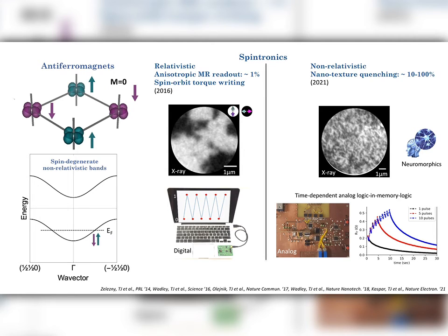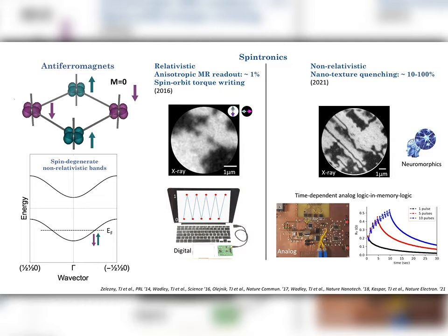And apart from imaging, we can use this electrical anisotropic magnetoresistance for the electrical readout, and then with the electrical writing and readout, we can demonstrate implementing experimental antiferromagnetic digital bits in these simple digital printed circuit boards and operate them, for example, from a personal computer. And these bits can represent logic zeros and ones corresponding to, for example, these two orthogonal directions of the Néel vector.